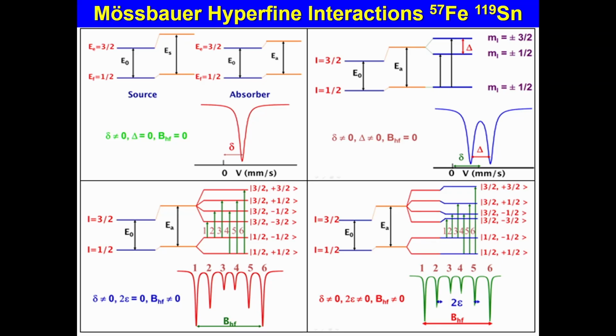Now, if we make a kind of short view, you have seen the effect of the monopolar electric interaction, the dipolar electric interaction, and the Zeeman effect, the magnetic interaction. But in a sample, you have to mix them, because physics would not be so interesting if there were no complexity. You will add the contribution to the Zeeman levels, and you will see a modification of the position of some peaks. But sometimes you have to take the opposite, because the quadrupolar interaction is much more important than the magnetic interaction. I did not put the scheme here because it's much more complex.